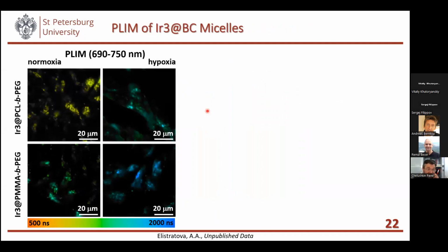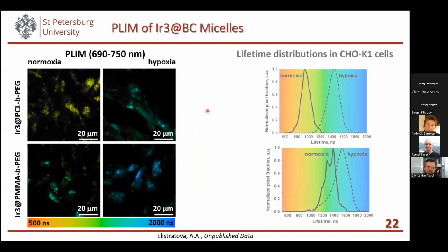imaging in this case. And you can see on the lifetime distributions that we can have here a very transparent difference between normoxia and hypoxia for the case of caprolactone-based micelles. And of course, PMMA-based systems expectedly gave only very little changes in their lifetimes upon degassing.